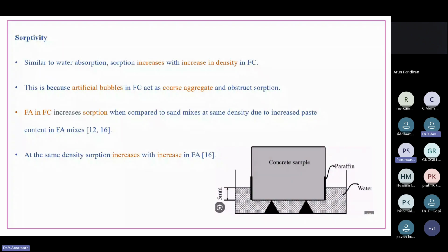Fly ash in foam concrete increases absorption when compared to sand mixes at the same density due to increased paste content. As we have discussed earlier, the same happens with the absorption property as well. At the same density, sorption increases with increase in fly ash content. Now, these are a few properties of foam concrete that we have discussed as of now.